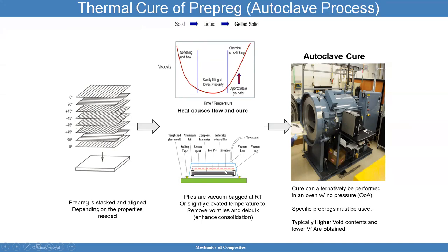Here, I'll go into this in more detail, but plies are vacuumed at room temperature or slightly elevated temperature to remove any open air that you may have inside. For example, I have a cell phone and I bought a protective film that's glued onto my cell phone. And I kid you not, it's full of bubbles. I didn't do it, it was a representative at the store, but I should have done it because I could have removed these bubbles much more efficiently. That's the kind of thing we're talking about here. I'm gluing one material onto another. That's what we're doing with these plies. We're trying to have the resin flow in such a manner that crosslinks are formed between these plies. The fibers will keep going in the direction they're going, but at least I can have some amount of consolidation.